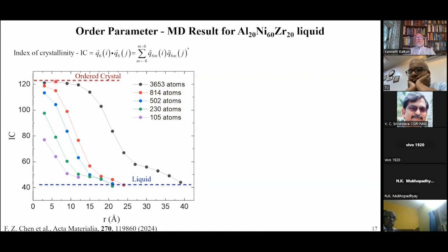One thing that comes out of this calculation, however, is that if I start decreasing the size of the cluster relative to the critical size, so these are all still larger than the critical size, but they're approaching the critical size, you still have the decay from the center to the liquid, but as you go to smaller and smaller clusters, you never get to the ordered state of the crystal. So for small clusters, the whole cluster is disordered, which means that initially when we form nuclei, those nuclei are very disordered. They don't look like the crystal phase that they're developing into. As they grow, they do.